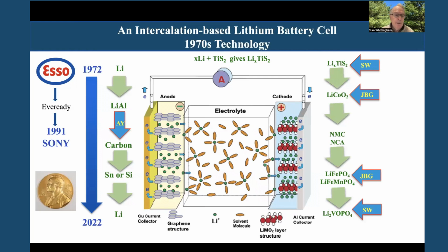So let's go through a little bit of the history so we can see where we come from and where we need to go. At the start, we started out with pure lithium metal. We saw those dendrites. So we used aluminum, and aluminum forms a 1-to-1 alloy. This works fairly well for 10 or 20 recharges, but then it crumbles. Akira Yoshino then developed the idea of using graphitic carbons, and that's what is now used in the anode. And these have been used effectively commercially since about 1990.